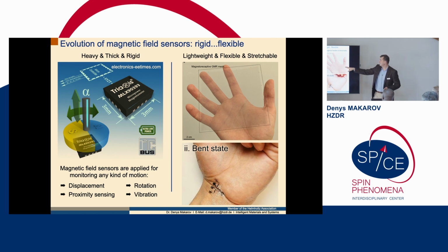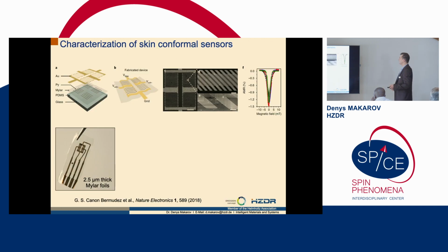So here what you see, you don't see anything, I think, because it's meant to be transparent. So it's a GMR, which is a giant magnetoresistance sensor, which is basically patterned in a way that you cannot see the film, which you can use for some applications. How to do it is very, very simple, because there is no change in the technology. You can play a little bit with seed layers and something like that, but in principle, the fabrication remains very, very similar. So for those people who work with thin film deposition, nothing will change, absolutely nothing.